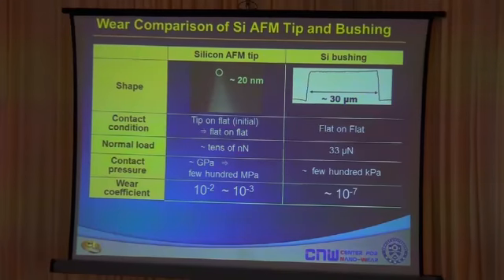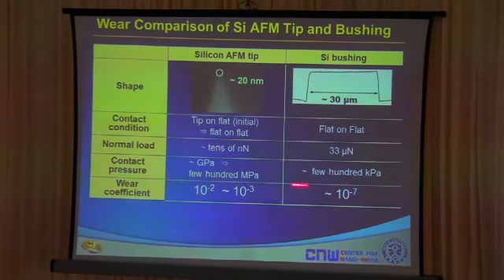It's showing us that even for the same kind of material, silicon, depending on the contact pressures, you can have tremendous difference in the wear coefficient. In the case of the silicon AFM tip, which is a radius of 20 nanometers, the normal load, despite the fact that it's only in the tens of nanonewtons, the contact pressure is in the gigapascal range, or hundreds of megapascal. In the case of bushings, despite the fact that the load was as high as 33 micronewtons, the pressure was only in the few hundred kilopascal range, and you can see that the wear coefficient is much, much smaller.